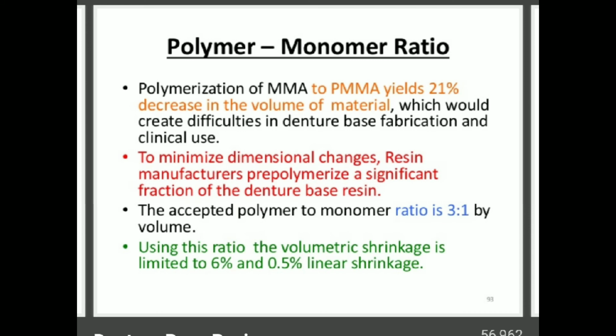Then as I already said, what is the polymerization reaction, what is the volumetric shrinkage when mixing, what is the linear shrinkage. The accepted polymer to monomer ratio by volume is 3:1, right? Volumetric shrinkage will be 6% and linear shrinkage will be 0.5%. Polymerization of methyl methacrylate to polymethyl methacrylate leads to a 21% decrease in the volume of the material, which would create difficulties in denture-base fabrication and clinical use. So, in order to minimize these dimensional changes, resin manufacturers pre-polymerize a significant fraction of the denture-base resin. That's why in the composition you can see in the powder part there are pre-polymerized powder particles. They use pre-polymerized particles in order to prevent the dimensional changes, right?